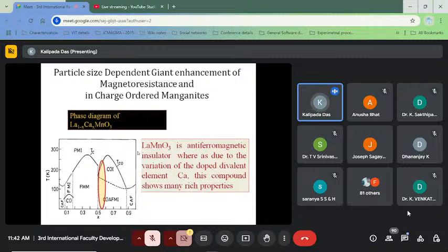And another method I have introduced is: can we get enhanced magnetocaloric and magnetoresistive behavior without using two samples? Can I get it in a single antiferromagnetic sample? Yes. Suppose LaMnO3 is an antiferromagnetic insulator, and if we dope a certain percentage of calcium, then its phase diagram will be like this. So we have chosen doping percentages of 52% and 54%, which are close to this phase boundary, and the ground state of the sample is still antiferromagnetic.